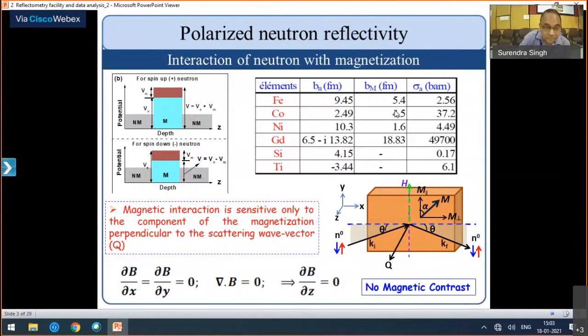And as a thumb rule, I told you on Friday - if our magnetization is perpendicular to the plane of the film, like in thin films mostly we say out-of-plane magnetization, like we have seen in all these memory systems where we have small bits along the perpendicular direction, which can be used as memory - those kinds of studies we cannot do by polarized reflectometry.